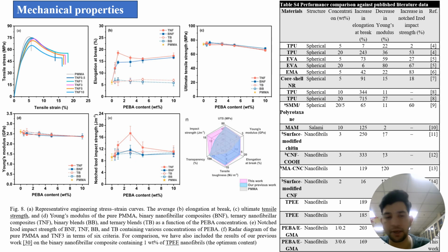Figure 8E shows the addition of PEBA nanofiber alone improved tensile toughness a little bit, but had minimal impact on the strength compared to PMMA. However, combined PEBA nanofiber with EGMA may greatly enhance impact strength. TNF3 exhibits the highest impact strength at 17.34 joule per meter, 87% higher than PMMA. No significant improvement in the impact strength was observed in binary or ternary blends.